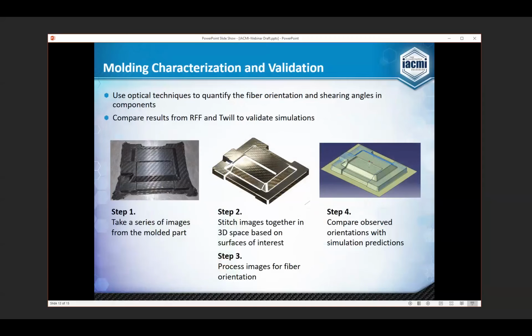And then the last piece is how do we validate our molding trials? So for our molding simulations, we can go through the trial that we just did with this M&T enclosure and take some images of that molded part and then use an image processing technique to pull those flat surface images off of the as-molded part and use those to compare with the fiber orientations that we would expect from our simulations. And so that work is ongoing right now to say, okay, how do we validate our fiber orientations? Because that closes the loop on our process.